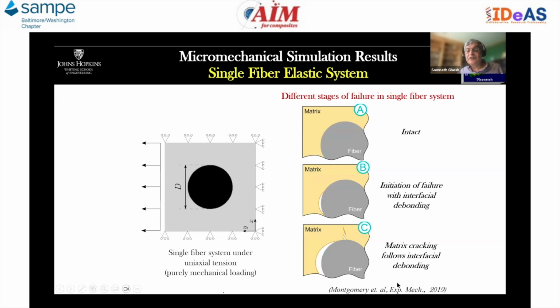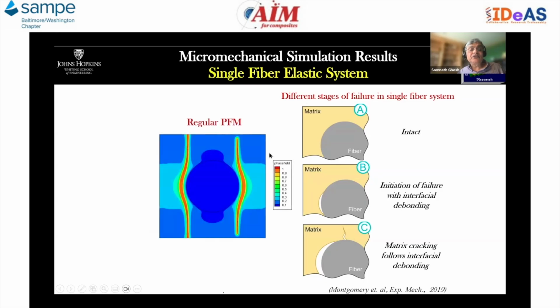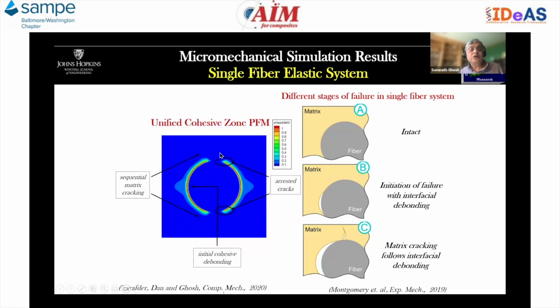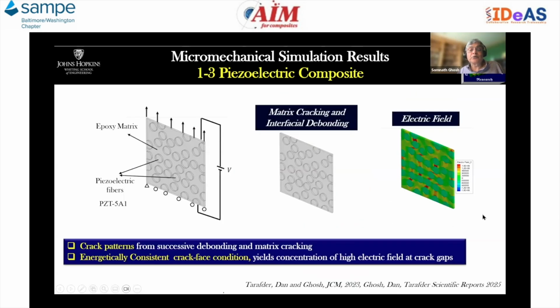Experiments in this paper have shown that the interfacial decohesion is not symmetric. What you see is that if you use just a phase field model, you would get a symmetric crack propagation prediction. On the other hand, if you incorporate this phase field based interfacial debonding together with the cohesive model, you do see the evolution of the cohesive zone at the interface, which is not symmetric. And this actually matches the experiments quite well.